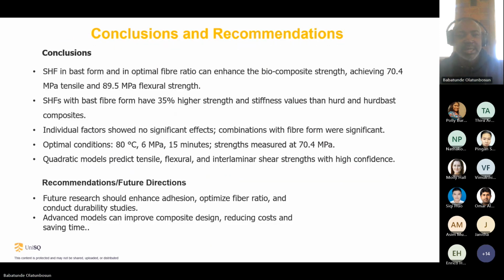Now, my conclusions, like I said: sun hemp fiber in bast form and at optimal fiber ratio gives about the best composite strength, and we were able to achieve about 70.4 for tensile and 89.5 for flexural strength. This shows that the bast fiber form has about 35% higher strength and stiffness value compared to hurd and the hurd-bast composite. It's worth mentioning that individual factors, I'm talking about the molding temperature, molding time, and pressure, do not have a significant effect. But when you combine them with fiber form, their effect is very significant.